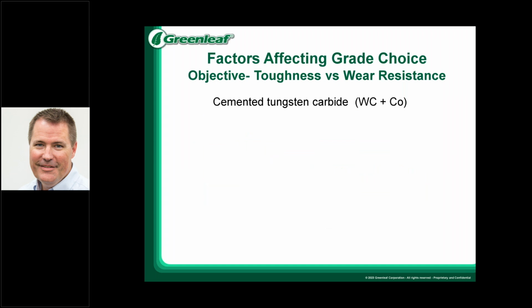When looking at the different grades and trying to determine what grade will work best, there's several different factors that can play into whether the grade is tougher or more wear resistant. Main ingredients in any carbide insert on the market is going to be tungsten carbide and cobalt. The amount, and the cobalt being the binder, the glue that holds the carbide grains together. The amount of cobalt binder in our inserts that we sell ranges between 4 to 10%,